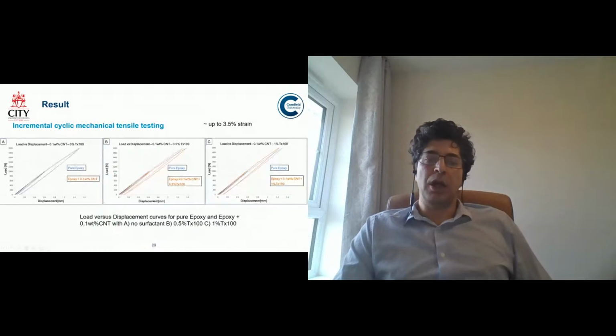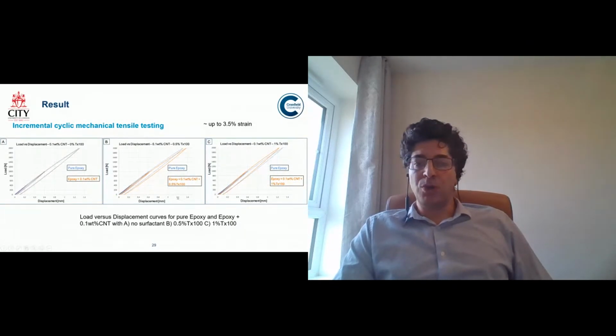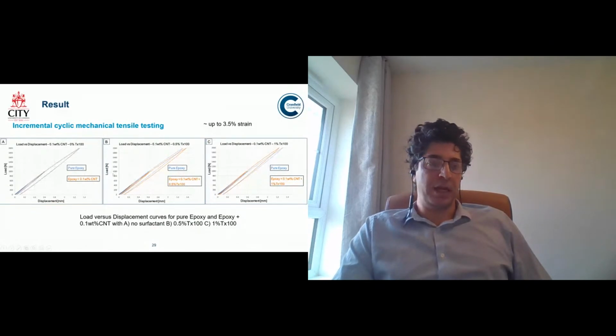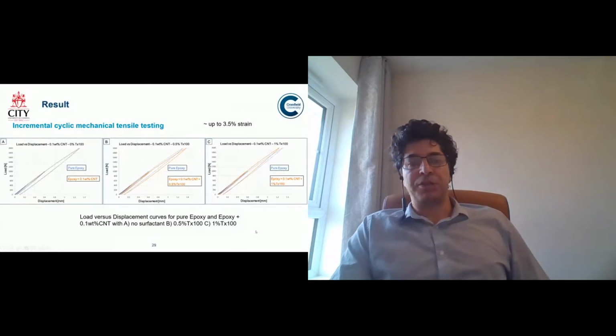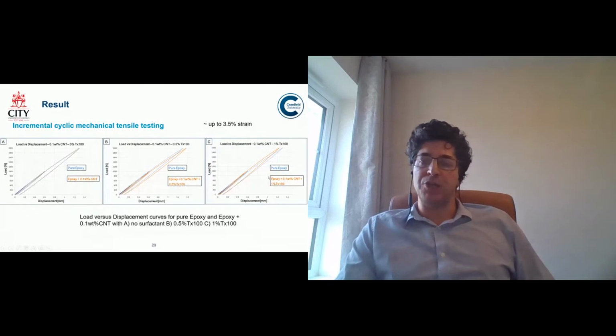I just wanted to say that look, if we do pure epoxy cyclic testing and epoxy composite testing with a carbon nanotube inside, with different dispersion and different things like that, you won't see that much of a difference in terms of mechanical response. This has been identified here by load versus displacement curves, and there's just a slight change or variation between these two curves. But in terms of the strain sensing capability, you would be able to achieve it.